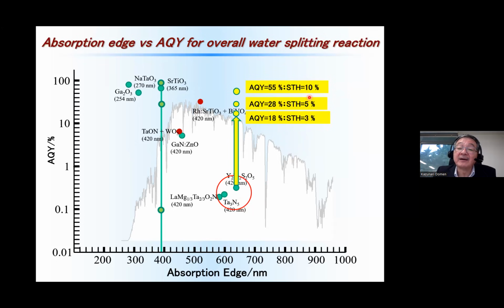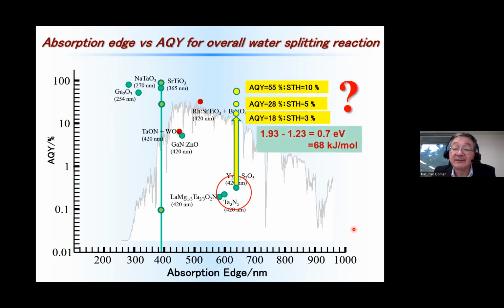If we achieve this number, we can produce a large amount of very cheap hydrogen. But the question is, is it really possible to achieve these numbers? So here, let me show one simple equation. The band gap energy of this material is 1.93 eV. And to split water into hydrogen and oxygen, thermodynamically, we need 1.23 eV. So the excess energy is 0.7 eV or 68 kilojoules per mole. And this is the driving force that we can use to enhance the activity or the rate of the water splitting reaction. And we believe that it should be possible to achieve these numbers.